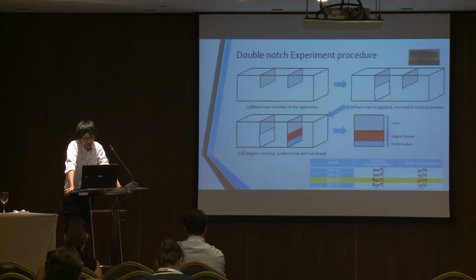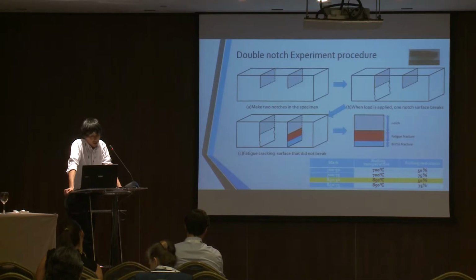In order to deepen the knowledge concerning the mechanism of brittle fracture occurrence of TMCP steel, a double notch test was conducted. The material used in the experiment is under this condition: rolling temperature 850 degrees Celsius, rolling reduction 50%. As shown in figure A, the test piece has two notches. By 3-point bending, the fracture driving force is generated equivalently at the two notch bottoms, and one notch surface breaks. So the other notch is preserved in an unloaded state just before crack occurrence. So, as shown in figure C, the fatigue cracking surface didn't break.